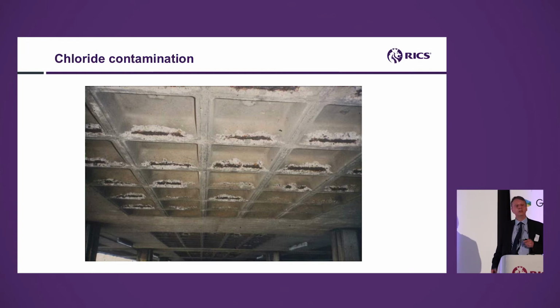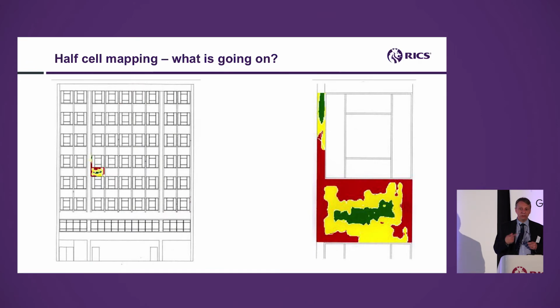So, two things. Difficult to repair, and it may be suffering from pitting corrosion. So if you're now preparing your schedule of dilapidations, you might want to be able to satisfy yourself that you've established the level of disrepair. Now, George Ballard, if you're going to his session this afternoon, is going to do some more on NDT, non-destructive testing. But I just thought I'd mention half-cell mapping, because this is one method that you may employ, well, you'd certainly commission, you probably wouldn't do it yourself, where you are attempting to measure the risk of corrosion having affected the steel. In this case, you're measuring the potential difference. You're drilling a hole, connecting electrical contact to the steel bar and then measuring currents. This will give you an indication of whether corrosion activity is taking place.